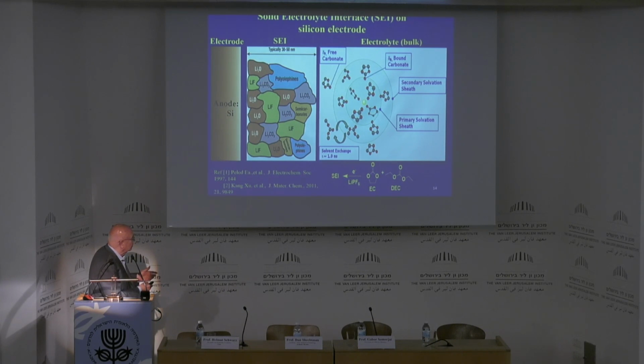This is a technology that's in constant change. Now it works with a silicon or graphite anode, and then the lithium is intercalated in the silicon. It goes into this electrolyte, which, because of polymerization, turns into a solid, and then it goes through the liquid to the cathode, and it deposits there. If you want to recharge, then you break the cathode bonds, and the lithium is diffusing into the silicon back, and you are ready to go again.